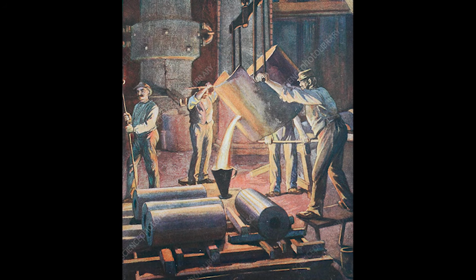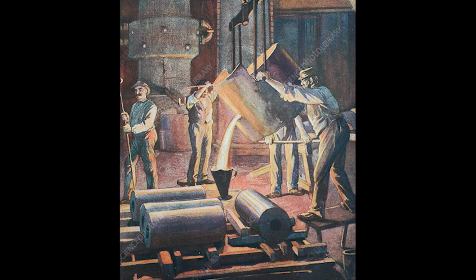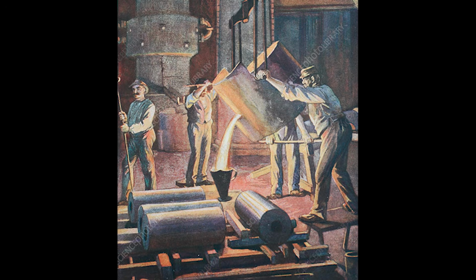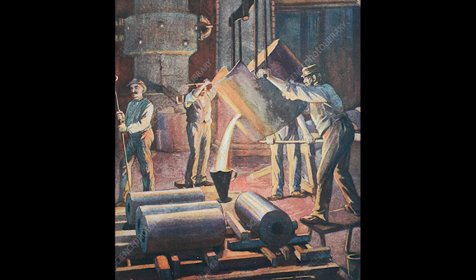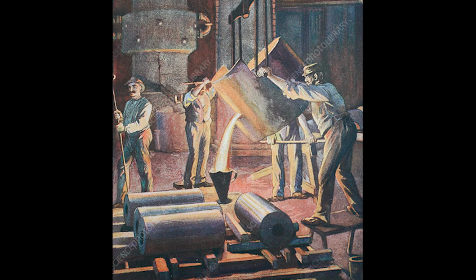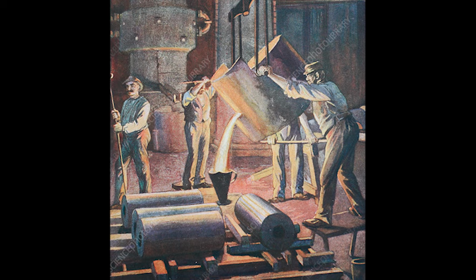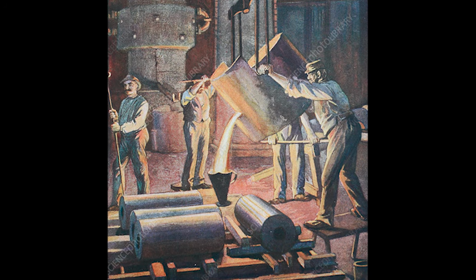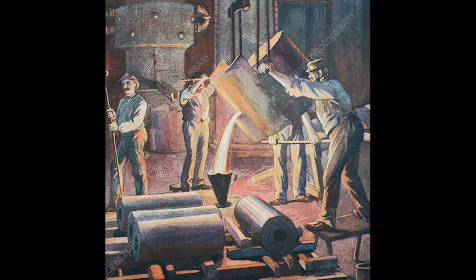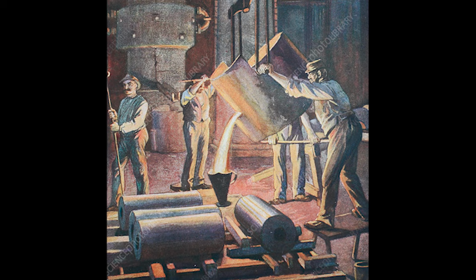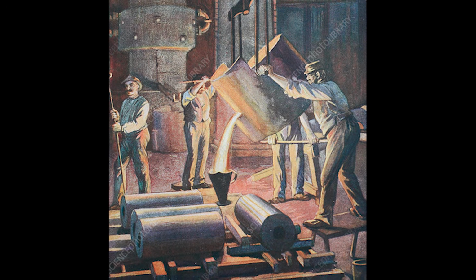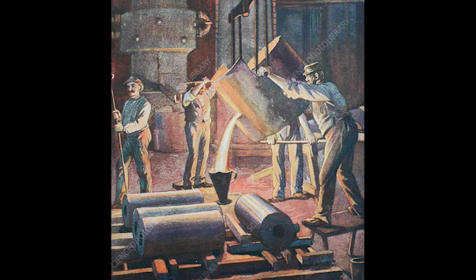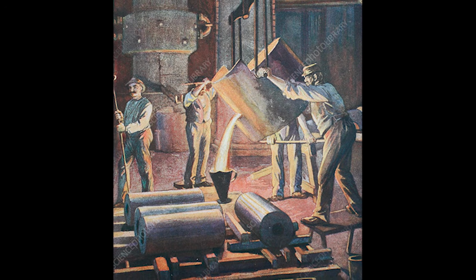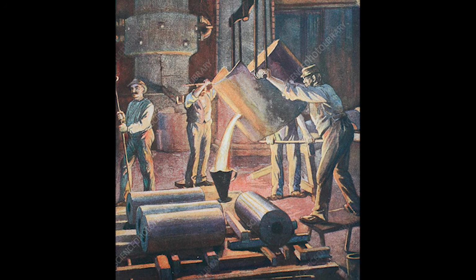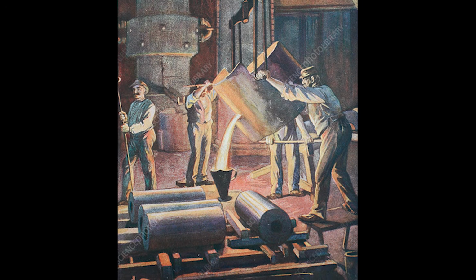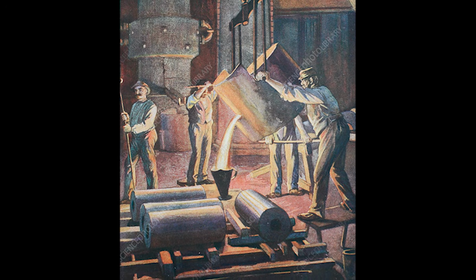Bundy seized the moment to explain the American approach. "We cast thick walls because chemistry doesn't negotiate," he said, running his hand along the substantial iron section. "When iron operates in deoxygenated hot water systems, it forms a magnetite layer. This protective film actually slows further corrosion. But aluminum requires precise pH control that becomes impractical when copper fittings and steel pipes are present in the same loop." The foundry supervisor called for the next pour, and the delegation watched as workers maneuvered a crucible of molten iron toward the waiting molds. The temperature reached 2,800 degrees Fahrenheit, hot enough to fill every detail of the pattern while maintaining the slow cooling rate that produced the dense, strong castings American systems demanded.